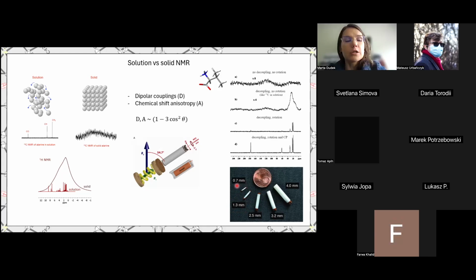The smallest rotor for now is 0.4 millimeter. I don't know if this is already available commercially, but Bruker made such a rotor. It's really, really small, so to pack it, you actually need to do that under the microscope. And obviously the amount of sample you can put in there is very small. And in a 0.4 millimeter rotor, you can spin 160 kilohertz, which is really, really fast spinning, although probably not all the interactions would be averaged out.